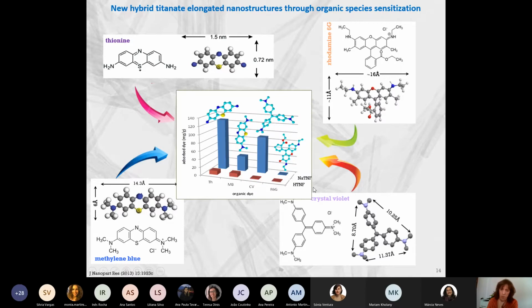So in this case, we were using titanate nanofibers, and if we start with the protonated nanofibers, we have no success in the immobilization of this species. But when we use the titanates with sodium in the interlayers, we can see here that in fact we have an adsorption that is very high for these materials. Of course, in the case of rhodamine 6G, we have no adsorption, and this is because of the steric effects that we have in this molecule. So we decided to investigate how these molecules are linked to the surface. Well, we decided to think about two limit situations.